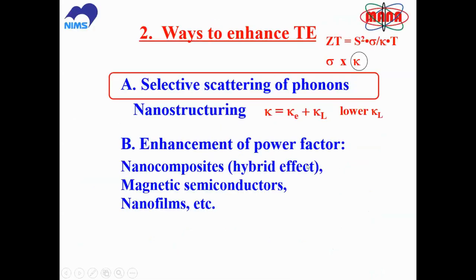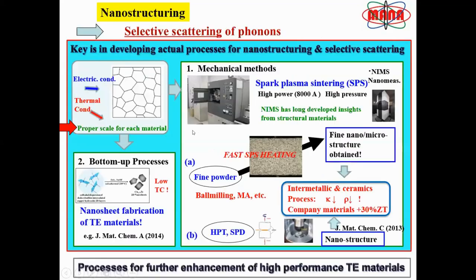So this is very interesting fundamental material science. The latter part, on blocking just the heat: if we look at the thermal conductivity, it's made of two parts. One part is by the electrical carriers, but we need the electrical carriers, so we can't do much about this. But the other part is the thermal conductivity carried by the material lattice, the phonons. So if we can lower the lattice thermal conductivity a lot, then we can increase the ZT, or the figure of merit. And one very powerful known way to do this is nanostructuring.